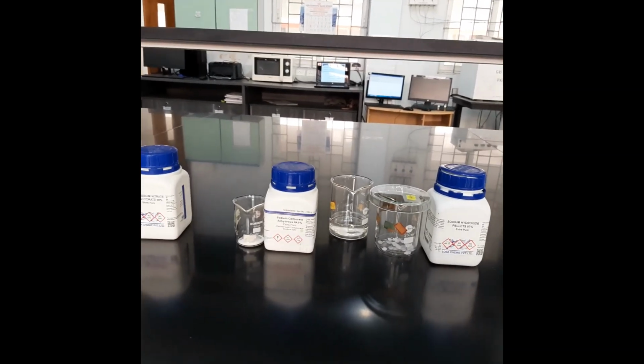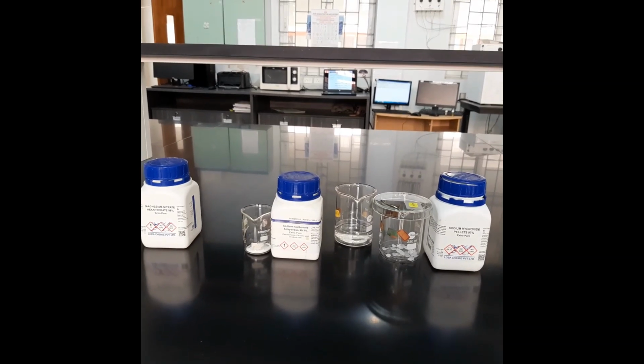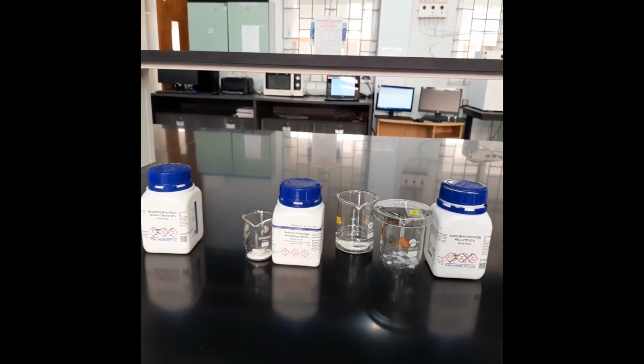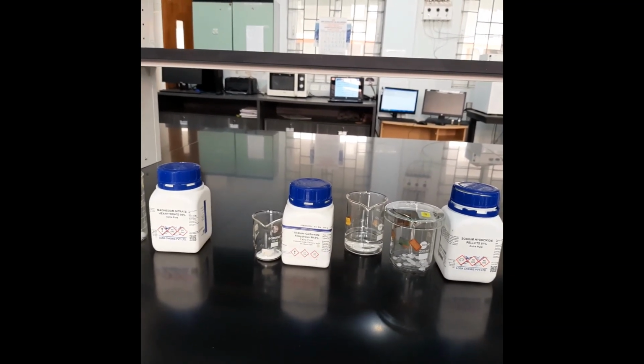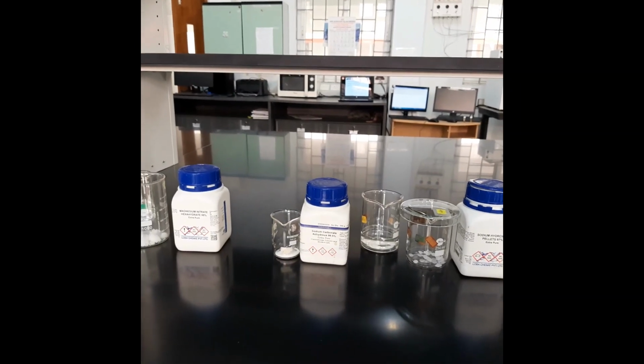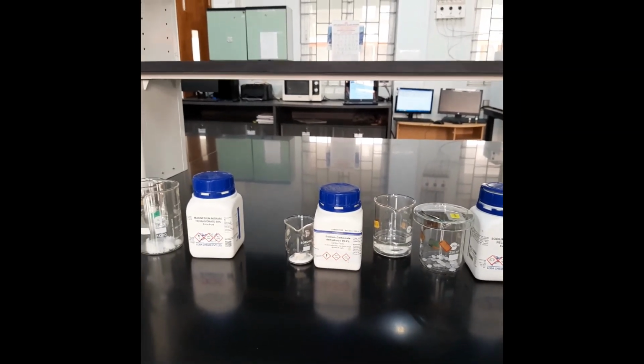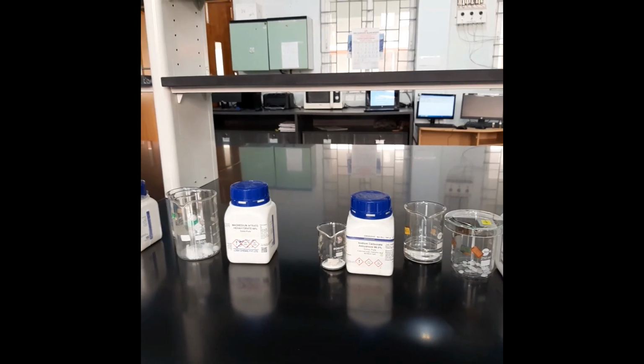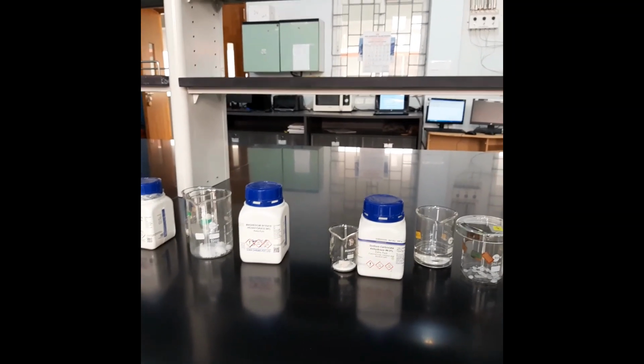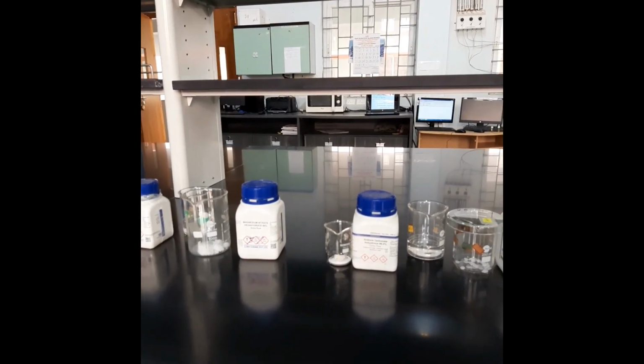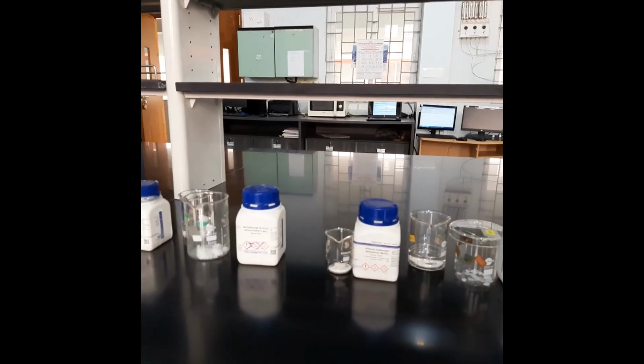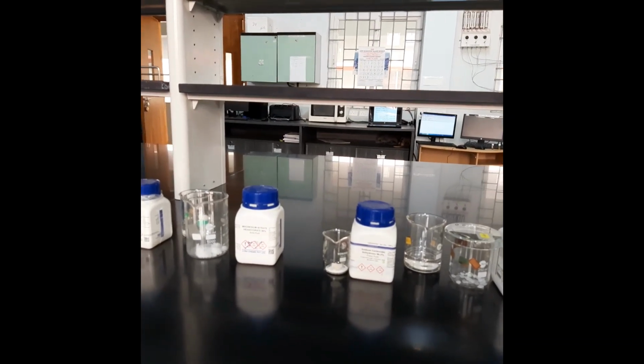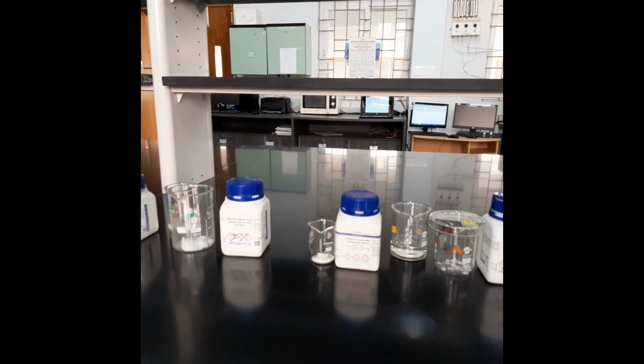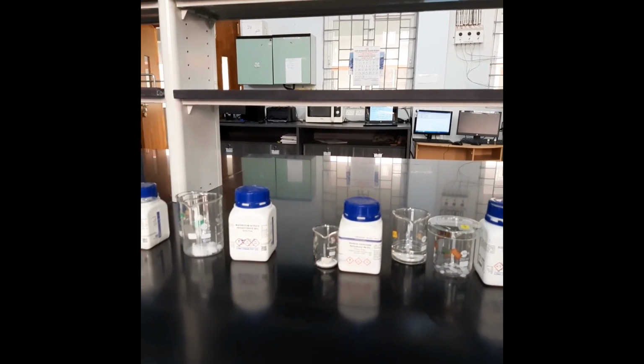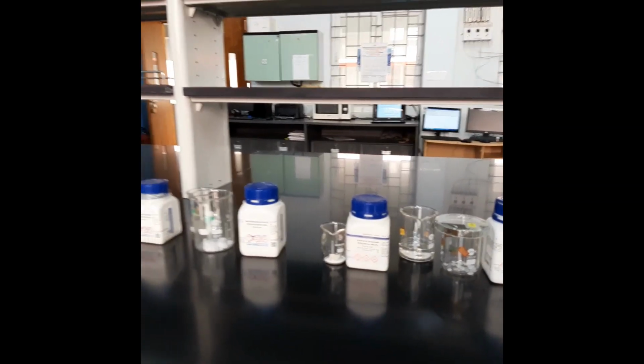Magnesium first forms the brucite structure, that is, edge-shared octahedra form the layered structure. Then aluminum will be isomorphously substituted. When aluminum substitutes in the magnesium sites, you are generating positive framework charge. The positive framework will be compensated by the carbonate anions. Initially it will be nitrate. Nitrates are quite labile, so they will be replaced with carbonate and hydroxyl anions. So this is the background behind the synthesis.